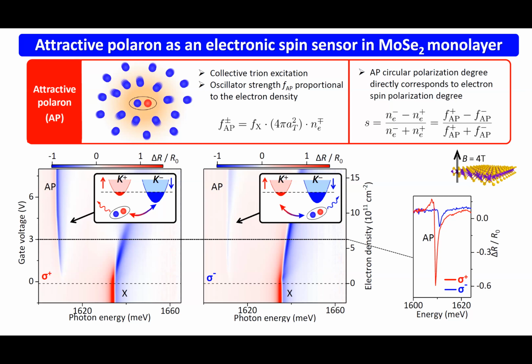So basically, the spin and valley are strongly correlated. When I talk about K valley electrons, these are spin up. The spin down band is about 20-30 milli electron volts above. And the opposite is true for the K minus valley.